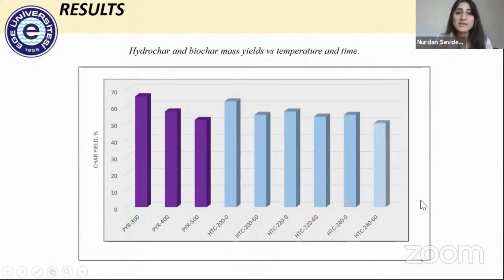When we come to results, here we have the yields of the chars. As expected, with increasing temperature, biochar yields decreased. The reason is that biomass decomposes more at high temperature compared to low temperature. We can say the same thing for hydrochars, but there are still no significant changes.